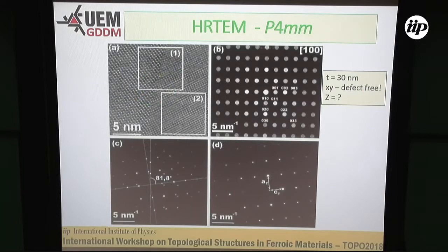We took two regions to do electron diffraction and also simulated it with this space group, an electron diffraction simulation. They have a very good agreement with this structure. That is this region 2. You have these A and C lattice parameters for the P4mm space group. When you do this electron diffraction in this area, in frame 1, we have the same pattern, but now tilted by 81.8 degrees. It's almost a 90-degree tilt between this side and this side of this interface. That interface is here.